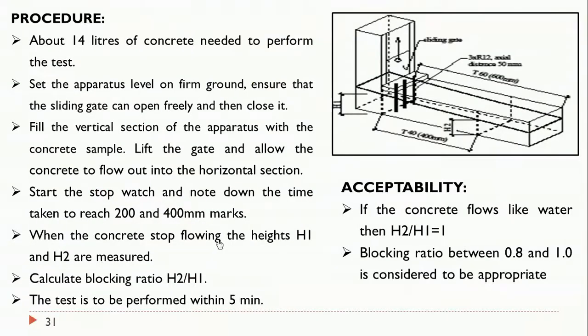So here, you see the same picture I have here. About 14 liters of concrete is required for this test. We have to set the apparatus firmly on the ground. The sliding gate, the movable gate, should open freely and close freely. There should not be any problem in the closing and opening of that sliding gate.